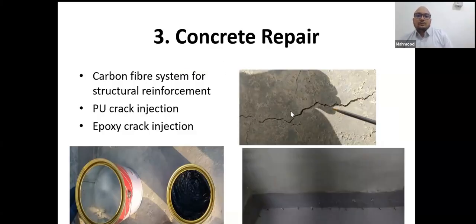Also, PU polyurethane injection is being used for filling the cracks. Why? Because there are two types of cracks: one is movable, one is non-movable. Non-movable you can treat with epoxy injection. When there is a water leak, even the water leak can be stopped by injecting with the help of PU, polyurethane. And where there's movement, you need to inject with polyurethane because polyurethane has flexibility, whereas epoxy is rigid.